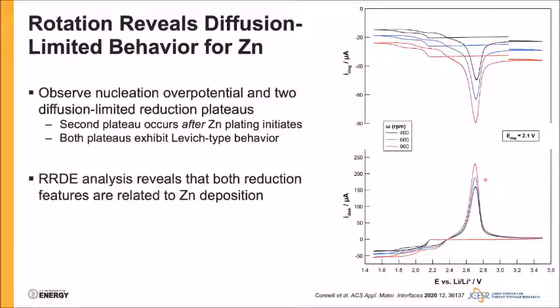very handy, where we drive constant zinc deposition on the ring electrode by holding the potential at 2.1 volts, corresponding to this first reduction plateau where we know zinc metal deposition is taking place. As we go to more and more negative potentials, you see a decrease in the ring current, corresponding to consumption of zinc by the disc electrode. And we see two distinct decreases in that current density, indicating that both of these reduction events are related to the consumption of zinc at the disc electrode.